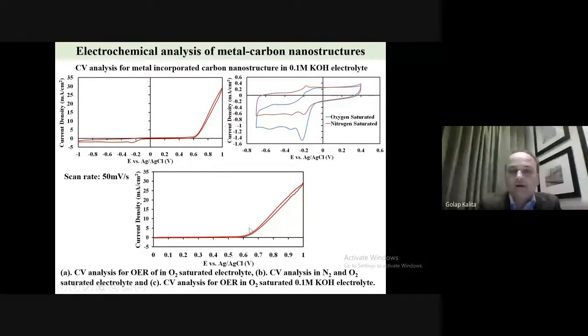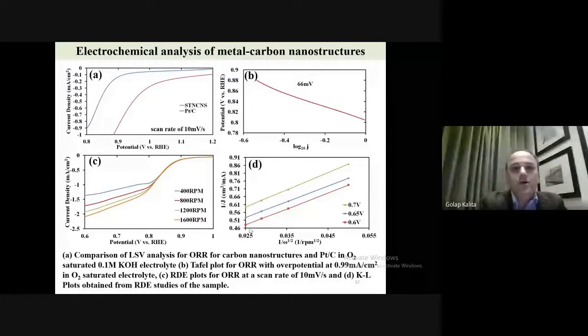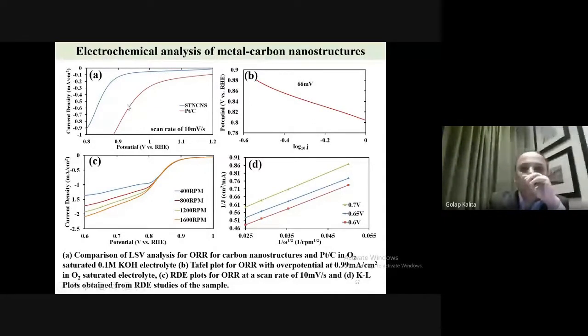This is a CV. We then compare this with platinum, which is the standard catalyst for fuel cell or ORR reaction. We can see this is for platinum, this is for our catalyst, and we have around 200 to 300 millivolt difference, which is not significant. So our catalyst also is quite promising with low overpotential as well. Again, we do the RDE measurement, and in case of this catalyst, we can get around 3.6, like 4 electron reaction.